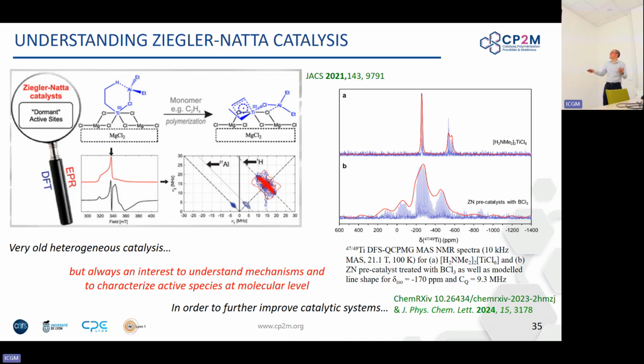And these are titanium NMRs, and they show you that when you start treating the precatalyst with BCl3, you homogenize the sites, okay? And they kind of resemble something that is fully chlorinated. And that's the goal of this chlorination agent, the BCl3, to increase the amount of that. If you were to do this titanium NMR without doing the Lewis acid treatment, you would not be able to observe anything because it's too heterogeneous, too many different titanium environments.